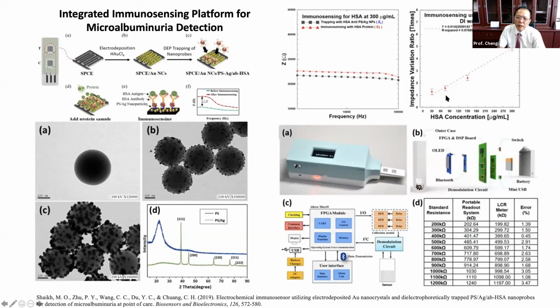Then we can have this albumin concentration, and this is the impedance variation ratio. But unfortunately, the detection limit is only 30 microgram. So 30 microgram is good enough, but not so good. So we try to develop another sensor.